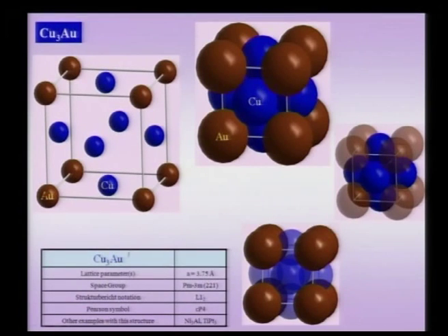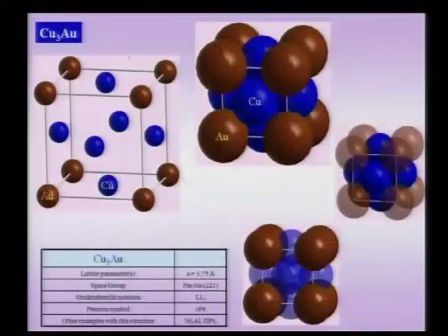Okay. Now the second thing, after starting with an original FCC lattice and creating this primitive crystal, I have to note is the stoichiometry. So I have 8 gold atoms making a total of 1 contribution to this unit cell in terms of gold. Now if I look at the blue copper atoms, which are colored blue for better visibility, I can see that there are 6 faces and each one of them is shared half between 2 unit cells. Therefore 6 by 2 is 3, therefore I have 3 copper atoms,